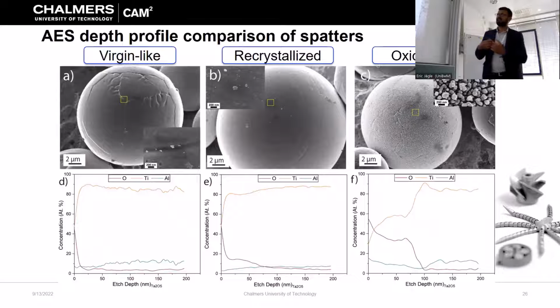And we did AES again on top of it to see what the difference is in the chemistry and the extent of oxidation. In virgin-like, there is a very sharp decrease in oxygen and a very sharp pickup in titanium, so the oxide layer thickness is quite low. In the case of recrystallized, there is a plateau forming here, so there is a little more oxidation compared to the virgin one. They have some kind of interaction with the oxygen present in the chamber. And in the oxidized one, we see a very thick oxide layer, around 75 nanometers on the calibration scale of tantalum oxide. So different types of spatters oxidize differently.